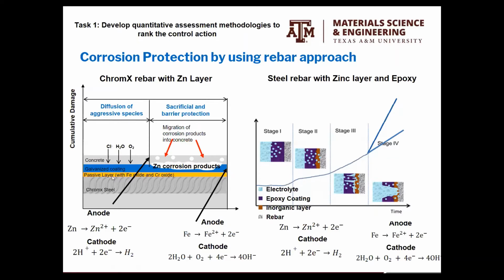The other system that we explore is that the passive layer will be different, which means that the rebar has certain components, and we name Chromex, for example, the Chromex steel, that has components. The theoretical aspect is that this layer will have an impact on the properties, but also we add the galvanized layer, and the hypothesis is that we have a cumulative damage constant with time until we reach the metal. But also when we reach the metal, we will have maybe a longer protection. Why? Because we have this passive layer, which we need to explore what is going to happen if the chloride goes and touches that layer.